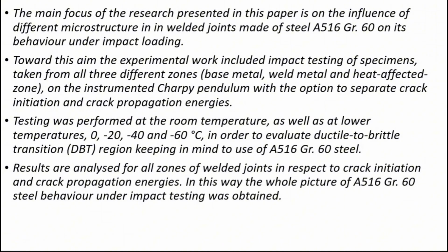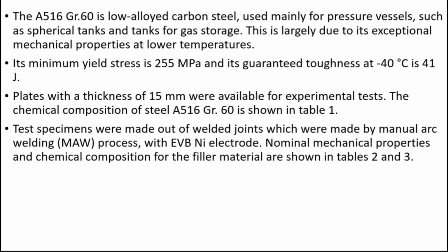Actually, our main task was to find out how these welded joints behave at -60, because there was an idea to use this steel as a pressure vessel, as a tank for liquefied CO2, which is operating at approximately -60. As I told you, this steel is a very low alloyed carbon steel used in pressure vessels, just as I mentioned, for storage. And it has, well, not exceptional, but good mechanical properties.